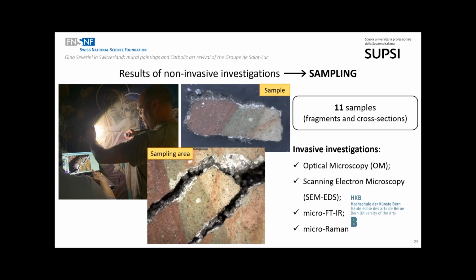By, for example, reflection FTIR spectroscopy, it is possible to obtain information exclusively from the surface layer. Therefore, the collection of samples is very important to understand the stratigraphy. In the case of the Severini's wall paintings in Semsales, 11 samples were collected, fragments then embedded in epoxy resin